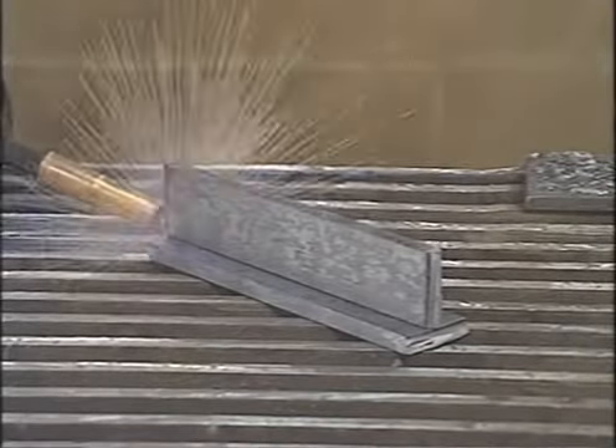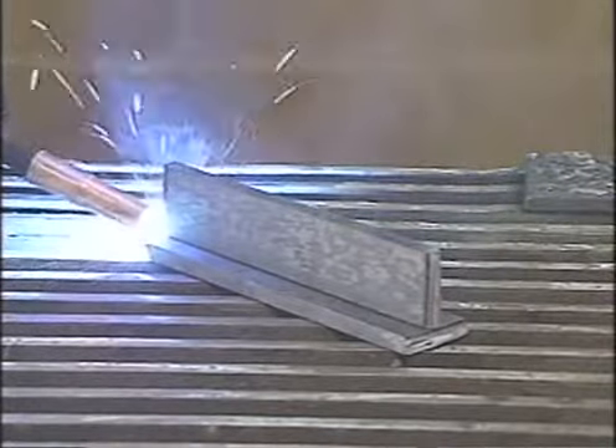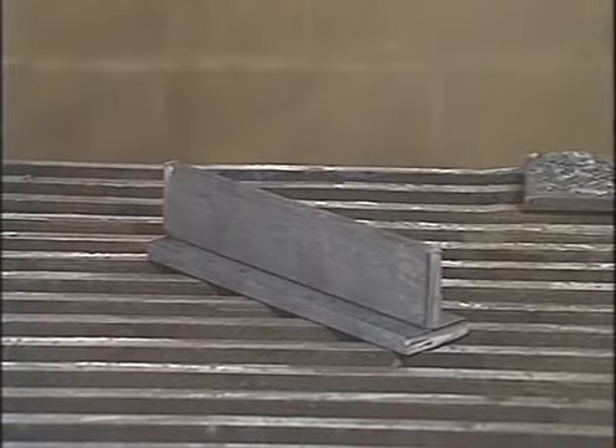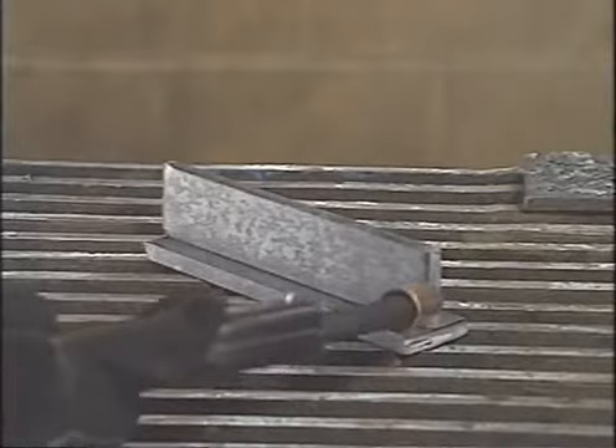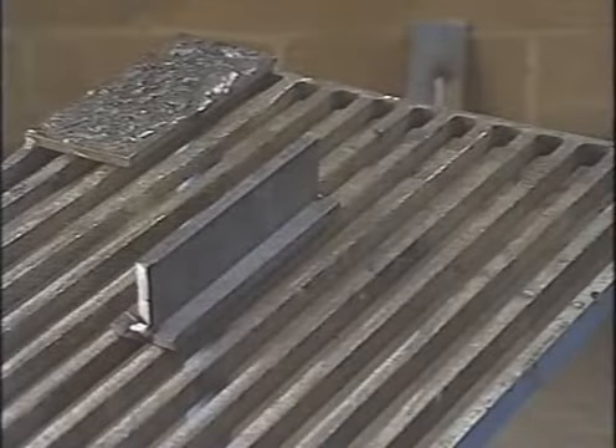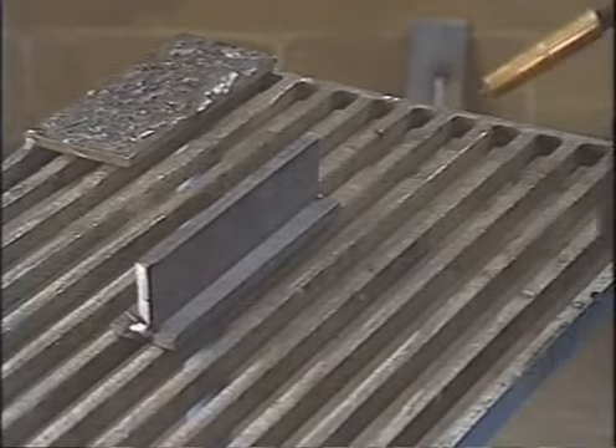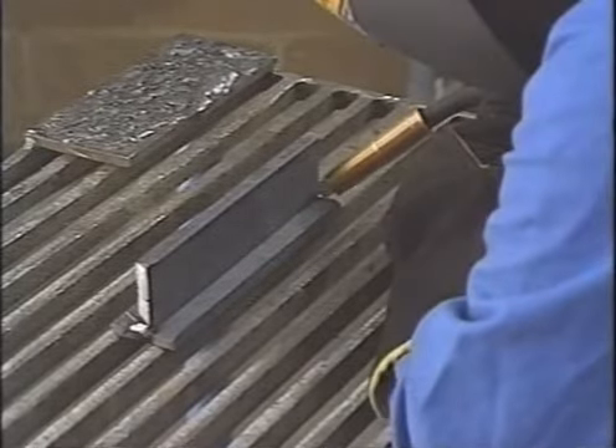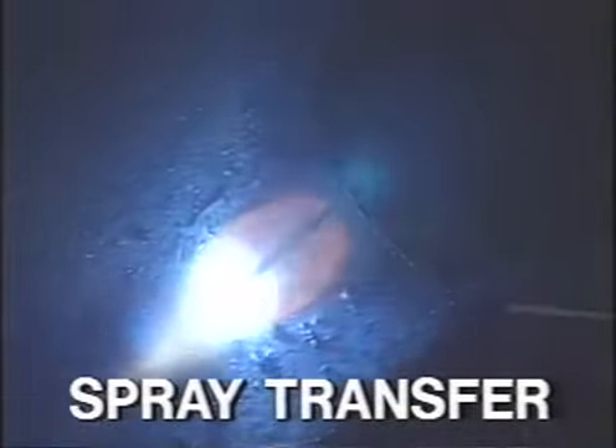The fillet weld, or T-joint, is achieved by setting the two pieces of plate at right angles to one another. After tacking, position the welding gun at an angle of 45 degrees. Commence the weld run using the spray transfer method to ensure sound penetration at the weld root. It is important that the weld is of equal size on each piece of parent metal.